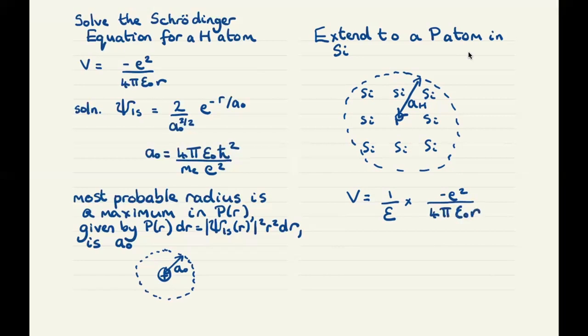And the other change, of course, is that the effective mass of the electron is not the free electron mass, but the effective mass of an electron in silicon. And so our hydrogenic radius, instead of being a zero, is 4 pi epsilon zero times the dielectric constant of silicon, h bar squared, divided by the effective mass of the electron in silicon times e squared.